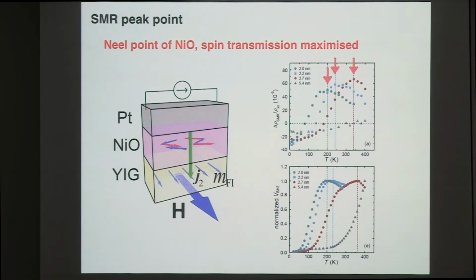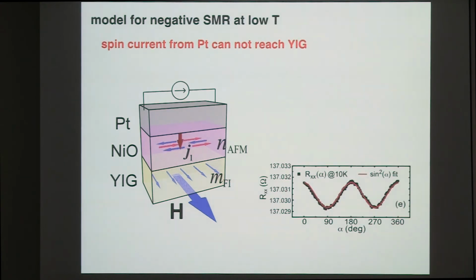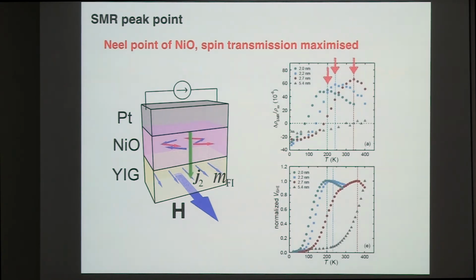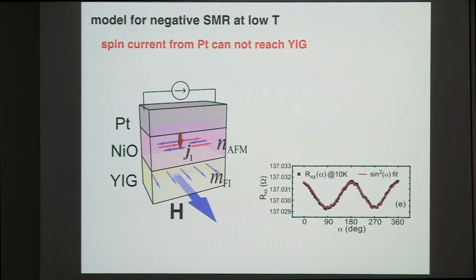So first, if you look at the data above the Néel temperature here, there is actually nothing strange, because the Néel order has not been established. So there is spin transmission, and you have positive SMR, pretty similar to the spin pumping result. Then you go to the lowest temperature, below the Néel temperature, where the nickel oxide will block all the spin transmission. Which means that the spin current can only be felt by the surface of a few layers beneath the platinum, and cannot really feel the spin by itself.